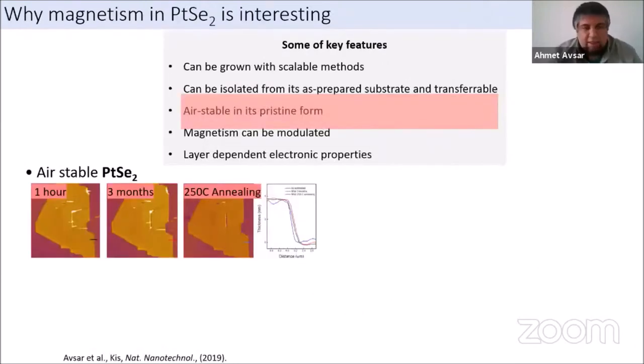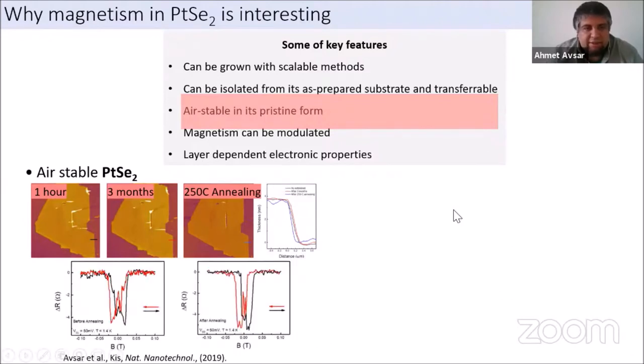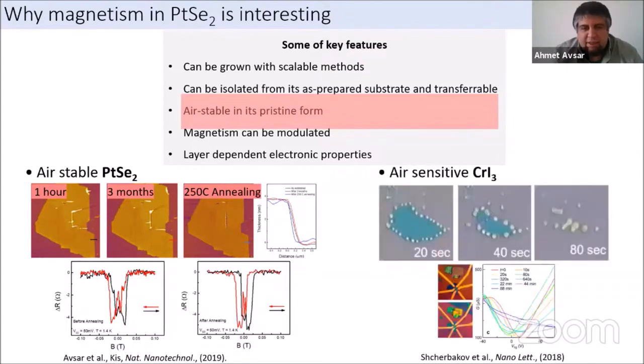Okay, so I think I have only a few minutes left, and I will be briefly discussing why this material is interesting. So this platinum diselenide, PtSe2, first of all, can be grown large scale, and it can also be transferred from one substrate to another one. So it could be used in applications, and also you can already see that it's very air stable. Even 3 months after, the material is still stable, and the magnetic response after 250 degrees of annealing is still stable. But if you compare, for instance, any of these intrinsic magnets that I introduced at the beginning of my talk, you will see that they are extremely air sensitive.